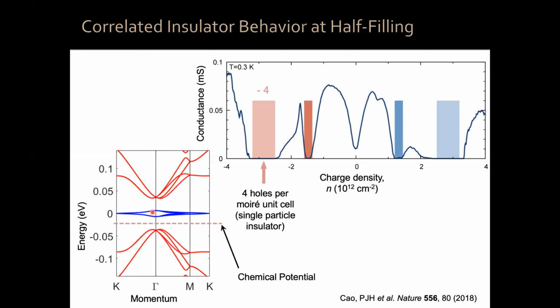So when the Fermi level, the chemical potential of our system, is here in the gap between the flat bands and the remote band, we are here in conductance. We have 4 holes per moire unit cell. Our chemical potential is at a band gap. So the system is an insulator, does not conduct electricity. We can shift with our gate voltage our chemical potential to be here in the middle of this other band gap. That corresponds to filling 4 electrons per moire unit cell. This is also a single particle insulator. That's why it doesn't conduct electricity.